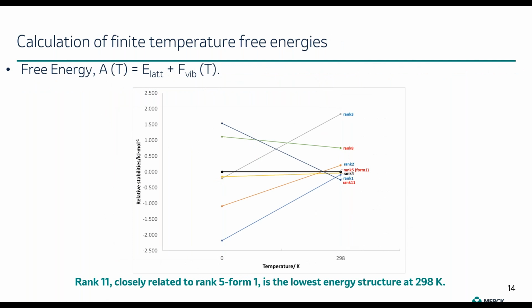So we went into finite temperature calculations. We calculated the lattice energy at finite temperature, and we saw a lot of re-ranking from 0 to room temperature, 298 Kelvin. And what we discovered was that at 298 Kelvin, the global minimum is rank 11, which is a crystal structure closely related to rank 5, which is the match to form 1. And at room temperature, several crystal structures are very close in energy.